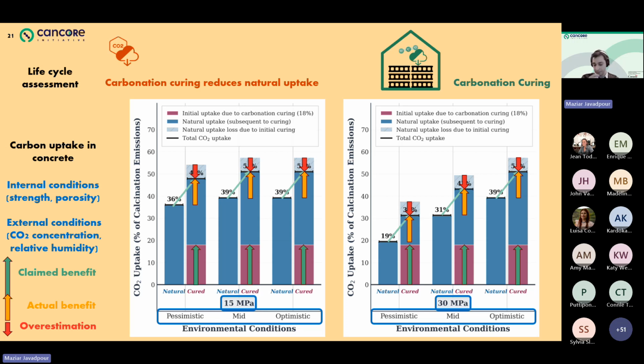But the issue is here. Let's assume that we have 18% of carbon uptake during our carbonation curing. And that means that we claim this benefit. The green arrows are what we actually would claim. But the actual benefit that we would get is these orange arrows, because as you remember, when we talked about that remarkable ability of concrete, carbonation curing will decrease the carbon uptake during the end of life and service life. So what we're really facing when we talk about carbonation curing and claiming credits is this little overestimation, these red arrows that you can see here. And this is something that we need to be very, very careful about.